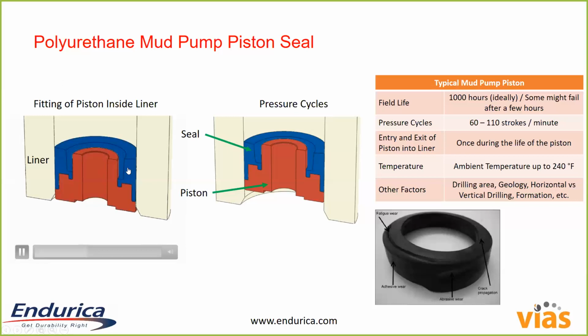This part operates at something like maybe 100-ish strokes per minute, and it's operating at temperatures that are up to 240 degrees Fahrenheit. And here's a picture of a failed seal with examples of where cracks start to initiate. So the point of this is to predict the life, and then hopefully be able to use that model to improve the life of the piston seal.